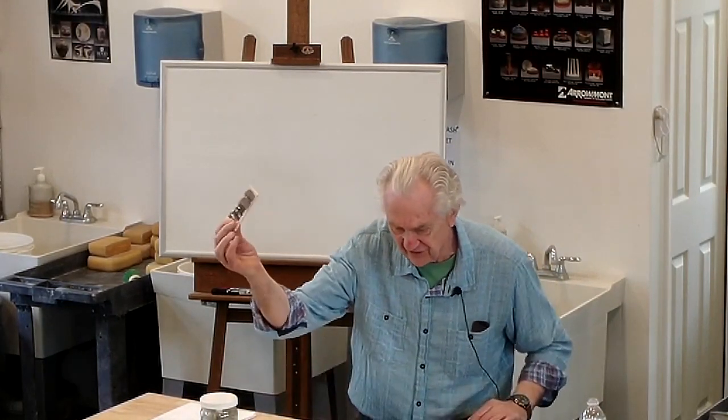So I just got some others, like this is a Cone 6 ash glaze, made with local clay and an ash glaze. This is basically just clay and wood ash. This is 1/3 clay and 2/3 wood ash. And this is a Cone 6. So just clay and wood ash, and I added a little cobalt to it to give it the blue color. It's a really nice, predictable, really simple glaze with 2 ingredients: clay and wood ash, local clay.